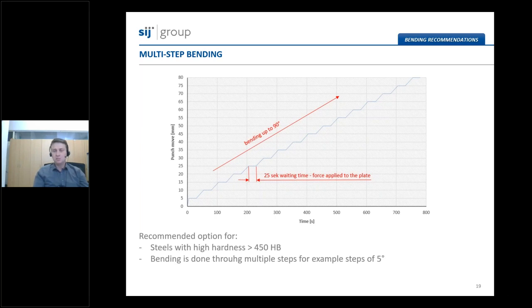So the bending speed here, which was used, was approximately 1 millimeter per second. And when the punch makes the 5 millimeter step, we wait approximately 20 or 25 seconds. And we are repeating this process until we reach the final angle. And I think that this type of bending is not necessary to be practiced on SIMAXX grades, but we recommend to use this on very resistant SIDUR 500 grade.